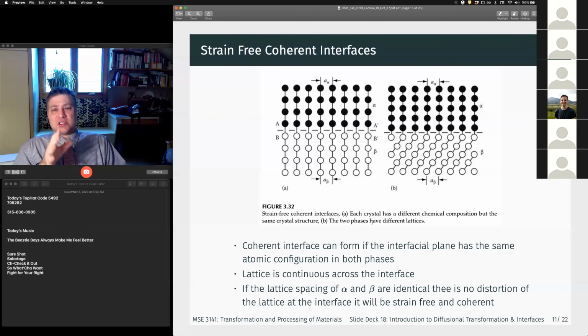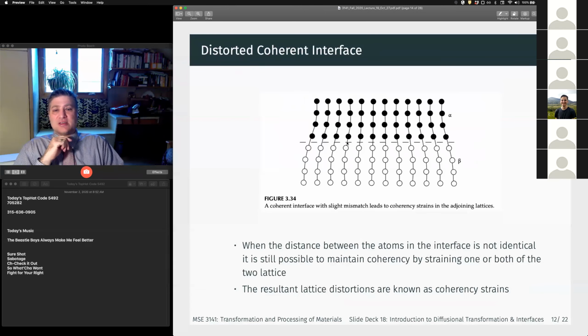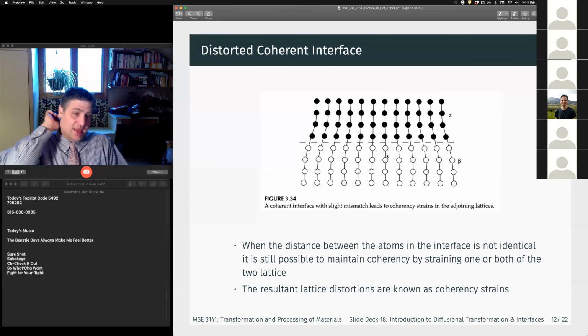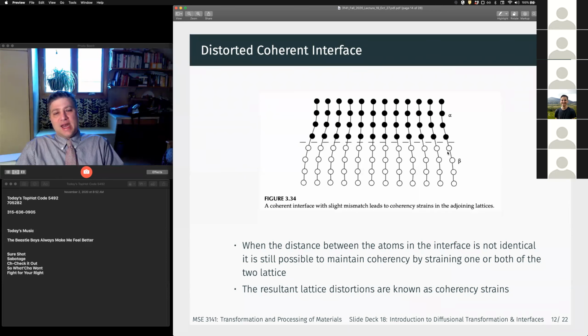Right, so that's the first type of coherent interfaces, what we call strain-free coherent interfaces. More commonly, if we have a coherent interface, they're slightly distorted, right? This is highly schematic, but it helps you get the physical picture. If the lattice spacing between alpha and beta are not exact, but they're close enough, I can still maintain a one-to-one correspondence across it. But I now have a strain.